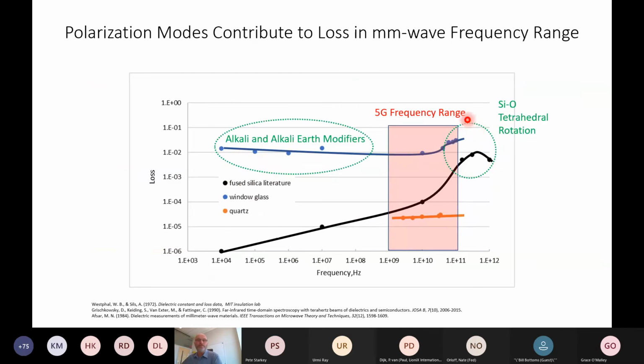But what's profound is really this graph, where now we're looking at the loss, right? So let's do this comparison between those materials I just showed, where here's the quartz, right? This is the crystal material. Here we're looking at loss, again, a log scale. So we're at 10 to the minus 5 range in our measurements. Let's not even add anything, let's just look at silicon oxide in terms of crystalline and amorphous. And what you can see then, the amorphous material, or fused silica, all of a sudden in our 5G range is going from the crystalline value of 10 to the minus 5 range, a little over, to 10 to the minus 2. So even though the permittivity didn't change very much, the loss changed 3 orders of magnitude.